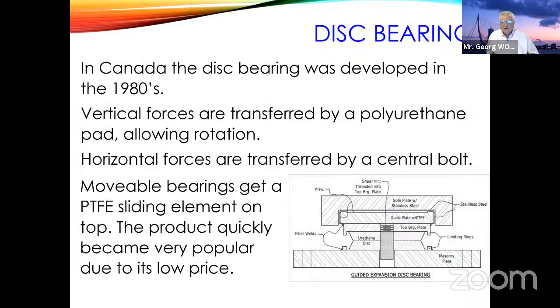Then we had another development in Canada in the 80s. The disc bearing was developed. The disc bearing is a polyurethane disc which has a center hole for a shear pin and which can be combined with the PTFE sliding parts on top. The vertical forces are transferred and the polyurethane disc allows the rotation. The horizontal forces are transferred by this bolt in the middle, and the movable bearings get the PTFE sliding element on the top, as you see it here. And this is a very low-cost bearing and became very popular. Here you see they have some rings outside to hold the urethane in the case of a problem.